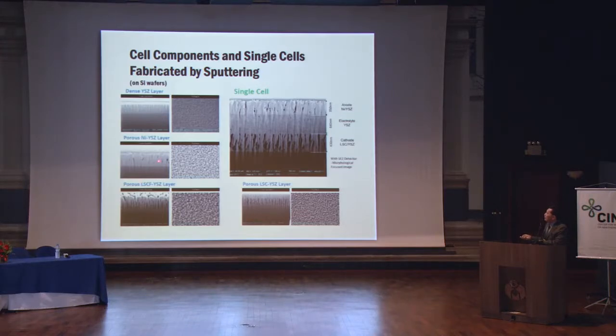We also deposit a porous nickel YSZ anode layer. Here we show the porous layer, cross-section, and top surface. Then the lanthanum strontium cobalt iron oxide, LSCF, cathode material on the YSZ layer, which also shows the porous structure, and another different cathode material, the lanthanum strontium cobaltite perovskite, also showing the porous structure.